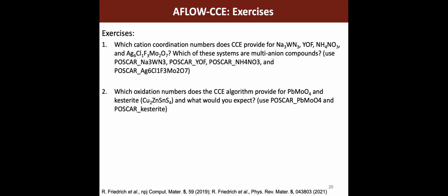How efficient is this procedure for finding oxidation numbers in magnetic materials? I mean, there is no restriction to non-magnetic materials in this sense. For instance, we have tried it on iron 2+ and iron 3+ systems, and it finds the correct oxidation numbers. You can even have magnetite, which is a mixed valence system of iron 2+ and iron 3+, and it does that correctly. So I don't see any obstacle in that direction right away.